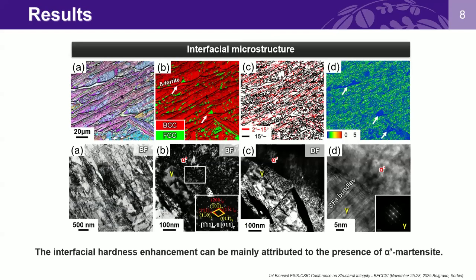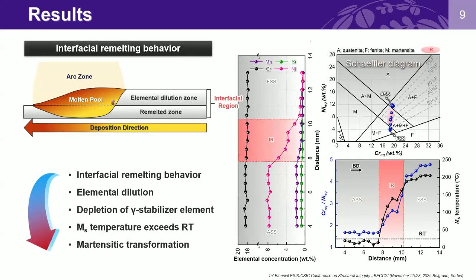To explain the interfacial hardness enhancement, the interfacial microstructure was examined using EBSD and TEM. The matrix is characterized by lath alpha prime martensite, accompanied by secondary phase delta ferrite and retained gamma austenite. Therefore, the interfacial hardness enhancement can be mainly attributed to the presence of alpha prime martensite. In fact, the martensite transformation can be attributed to the interfacial remelting behavior.